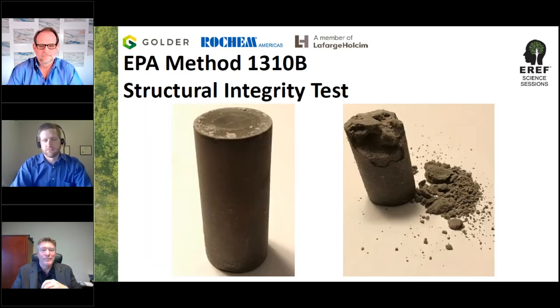The one on the left was compacted 15 times, and you can see it maintained its integrity quite well. The one on the right had a different binder in it, and it did not withstand the compaction test anywhere near as well. Why this is important is when you are finally done, you take either the whole monolith like you see on the left or the pieces that you see on the right, and you do an SPLP extraction on them. This is, again, per the EPA method 1310B.